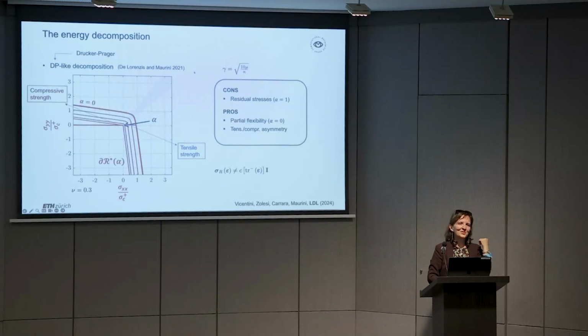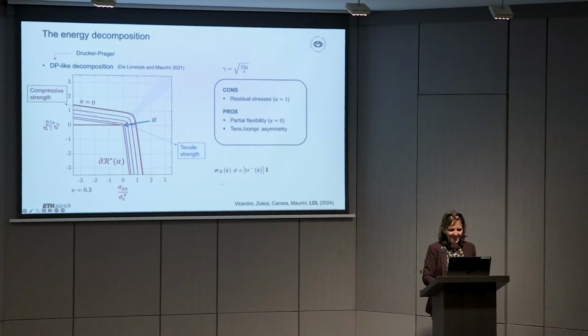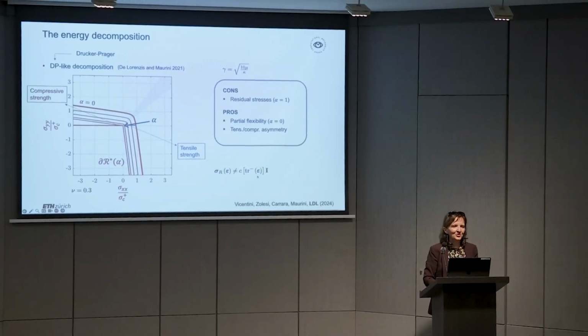So to respond to our friend Oscar, Corrado Maurini and I published a paper in 2021 where we came up with a new decomposition that was designed to be more flexible. So to give us a tensile strength and a compressive strength that you can calibrate as you like. So essentially we had a variational model with one additional parameter. I don't have time to talk about the model. But what we didn't realize at the time is that the residual stress, because we didn't quite know about these requirements that by now are so clear, but they were not clear some years ago. So we didn't realize that the residual stress was bad.